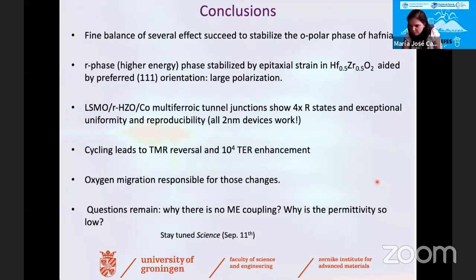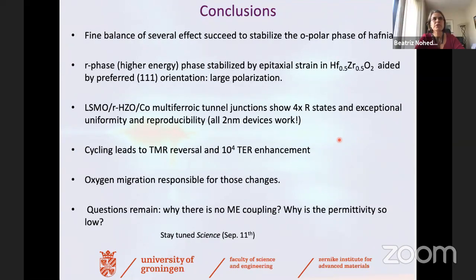Okay, we have a question by someone I don't know. Why do you attribute the change in spin polarization to the cobalt interface and not to the LSMO, which is subject to strong steric pressure changes due to the vacancy pumping? The particular changes that we see have been earlier associated, in other tunnel junctions with STO, I believe, with cobalt. People have observed similar TMR reversal. So that's why we thought it could be related to cobalt.